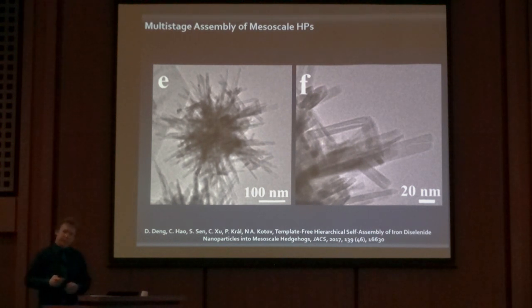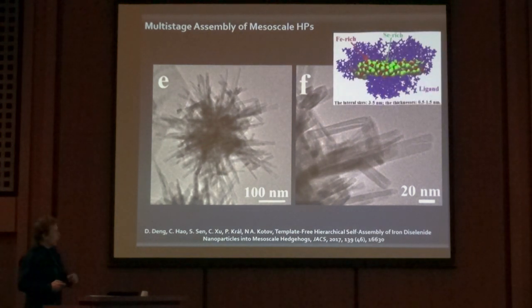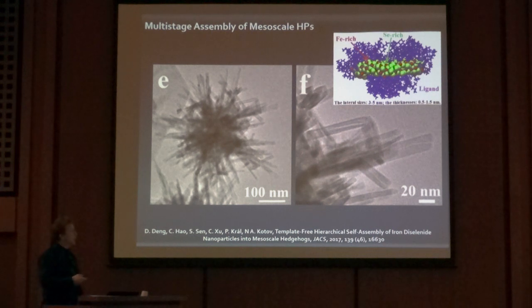There is nothing really complicated in making them. We just need to add a certain degree of anisotropy and affinity of the particles to the mobility of the particles which is provided by the fluid solvent. Due to that anisotropy and the oriented attachment at the edges, they can form these chains.